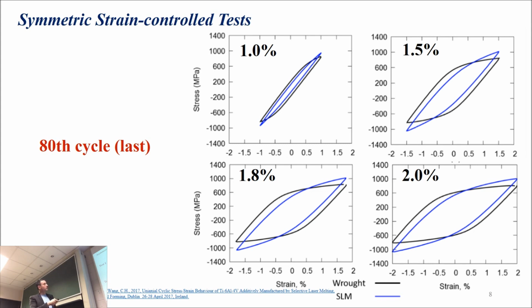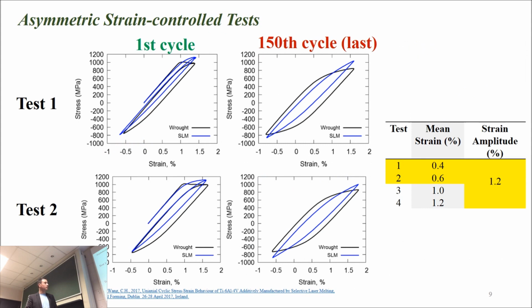So what we expected to see was actually softening, cyclic softening, and what we see here, actually this is happening for both, for the wrought material and the SLM material. Again, the capacity of the SLM material to undergo plastic deformation, the plastic energy dissipation capacity, as we call it, is, let's say, heavily impacted by the manufacturing process. Similarly, for test 3 and 4, we see the results which are consistent with test 1 and 2.